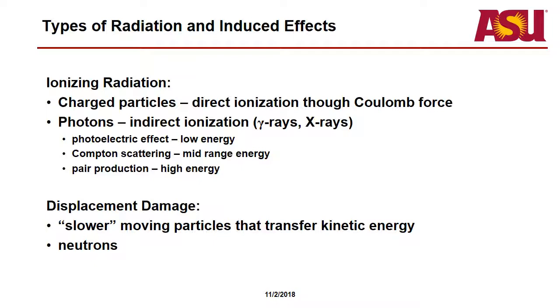And then besides ionizing radiation, there's also displacement damage. Once these charged particles start to range out, meaning they've lost enough energy that they're no longer interacting with the matter around them through Coulomb forces, they become more ballistic. So you'll have elastic scattering and inelastic scattering.